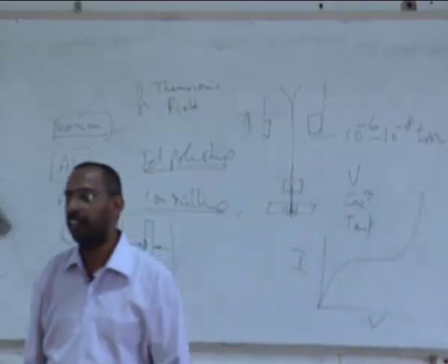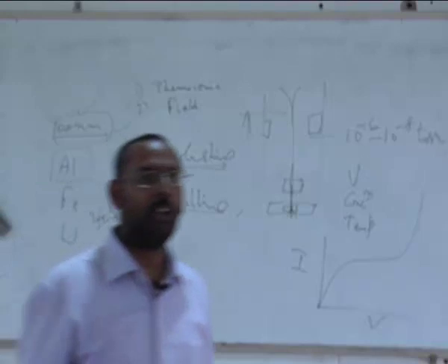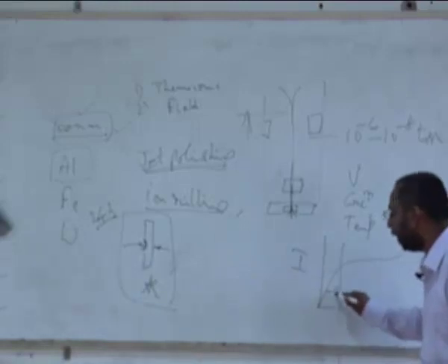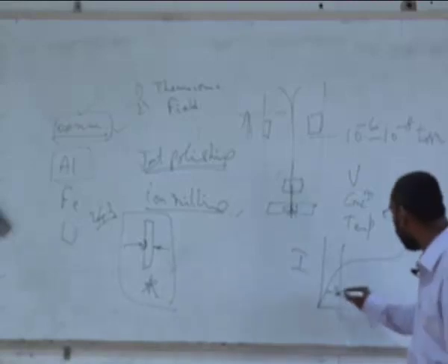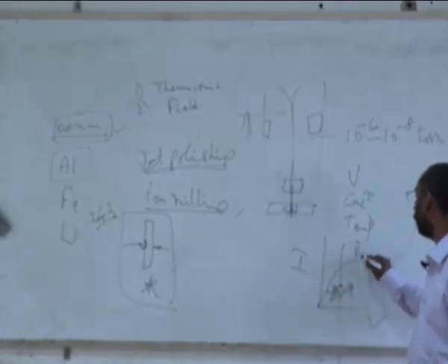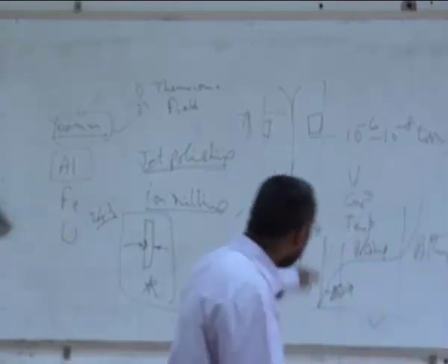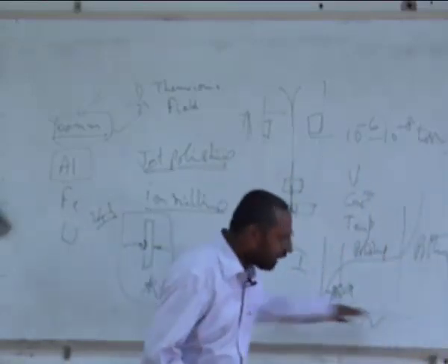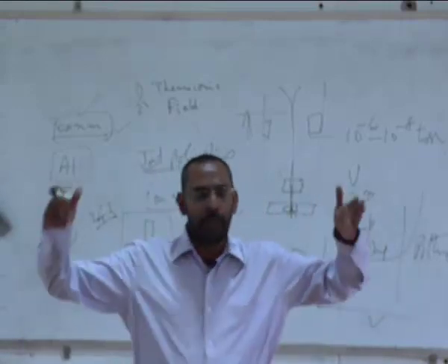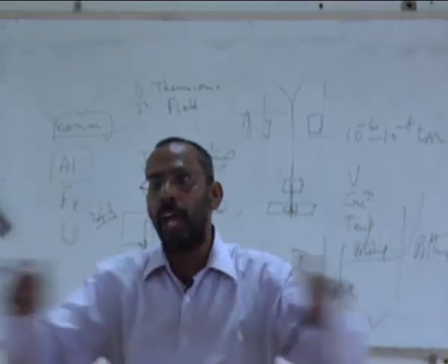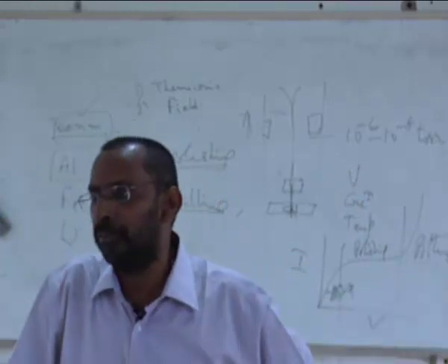If you have gone through any practical course on physical metallurgy, people would have talked about this. This part is called what? Yes, it is called etching. This is called polishing. And this is called pitting. If you are in the polishing domain, even if you vary the voltage, the current does not change. And that is the best domain where you should actually do your electropolishing.